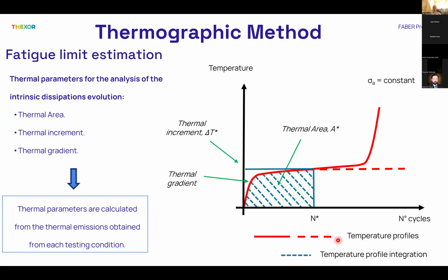In order to investigate the intrinsic dissipations produced during the fatigue test, thermal parameters have been properly developed over the years, and these thermal parameters are calculated from the thermal profiles obtained from a certain fatigue test in which a certain stress amplitude is adopted.